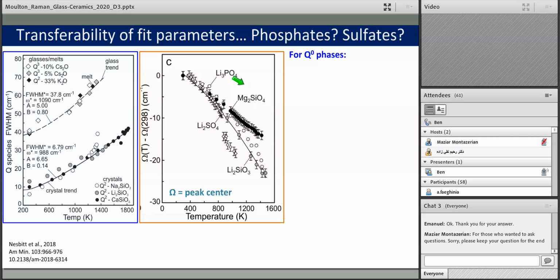The shift is a little bit different because the center is different for the glass systems. But if we look here, on the left-hand side is the same plot for the full width half max of the glass species. On the bottom is the crystals, on the top is glasses. If we heat up a crystal to its melting point, the full width half max happens to coincide with the full width half max of glass. And if we heat up the glasses, the trend here is exactly parallel, despite having completely different compositions.